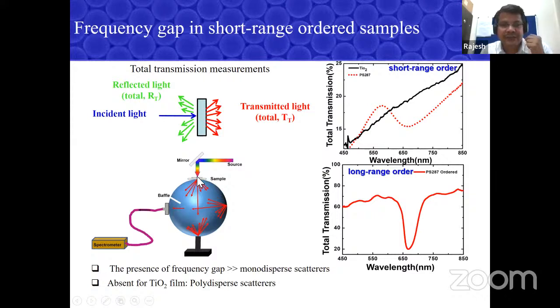So what we did, we took a sample here, and we launched white light, and we measured an experiment called total transmission. Because your sample is disordered, you launch light, you get reflection in all directions and transmission also in all directions. Because these are disordered, the light is scattered in all random directions. Whereas when you have a perfect sample, you don't have much problem because most of the light comes in a straight line, in the ballistic direction.